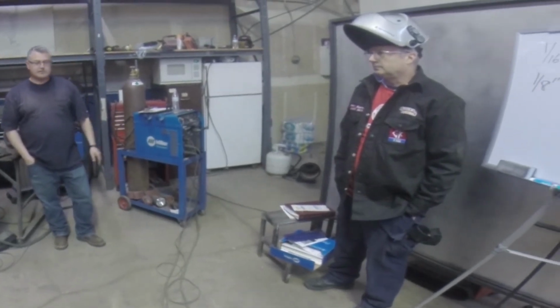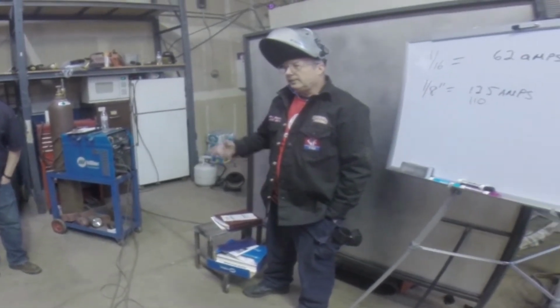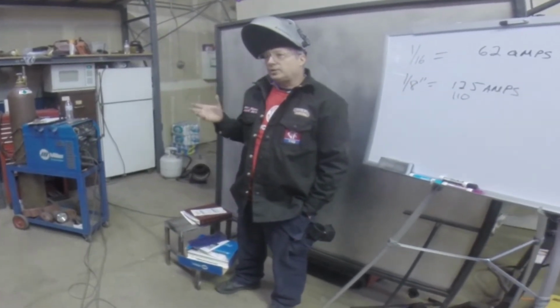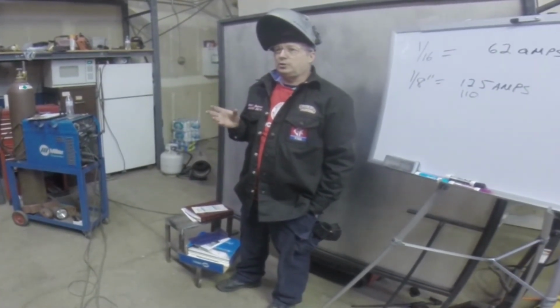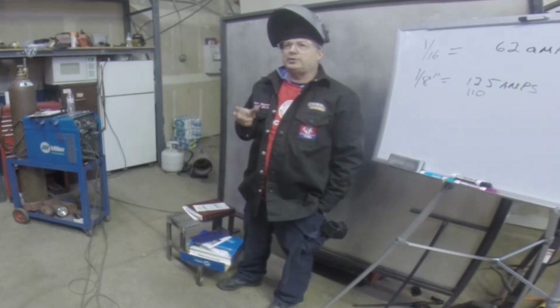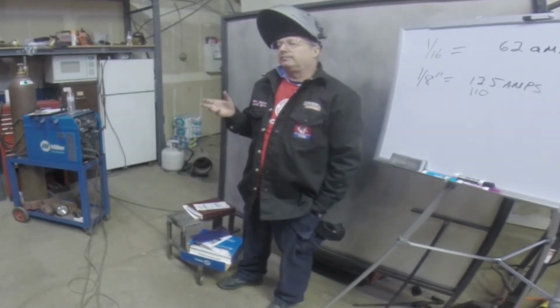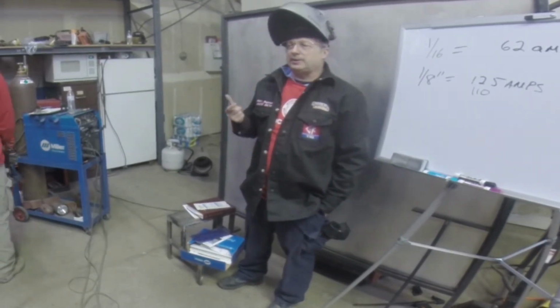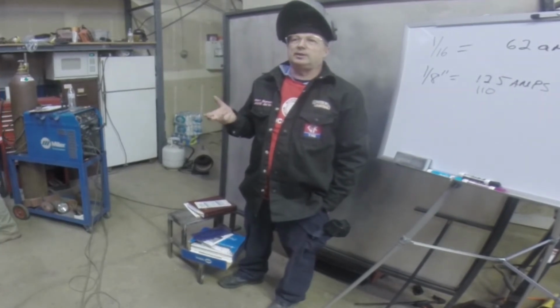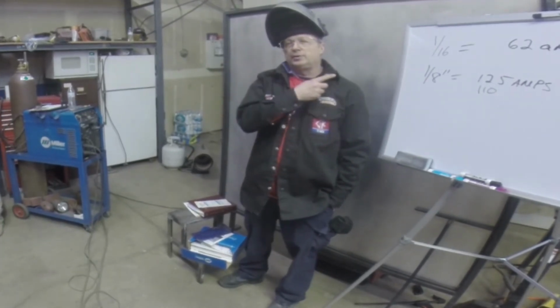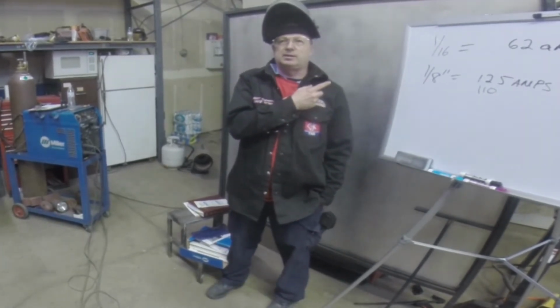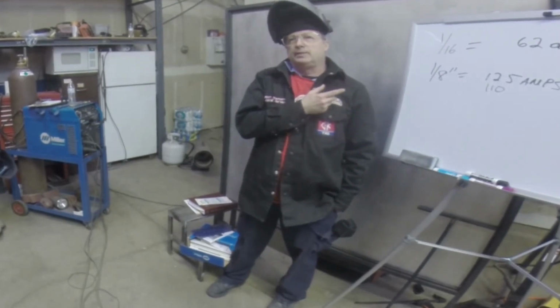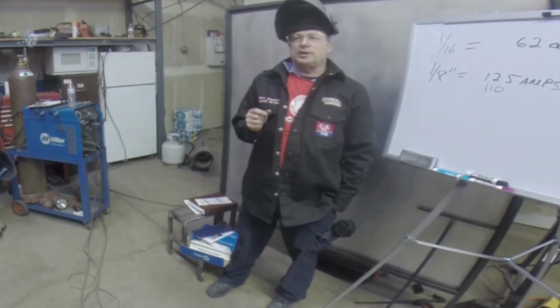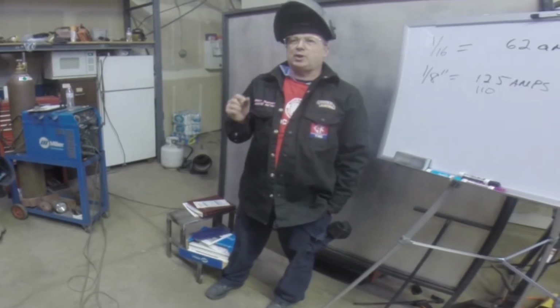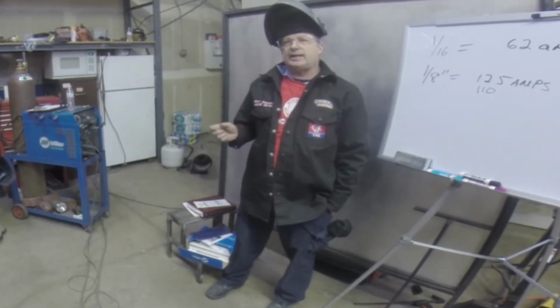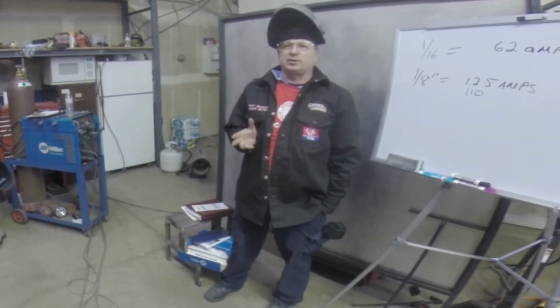It's awesome that Rich is teaching us this stuff. Yes, amperage, like you say, is very critical. In certain materials, you don't want to put too many amps in or you destroy the material. Most of you will probably never see it, but there are materials out there called Hastelloy. There's a company doing a mine outside of Las Vegas, and they're putting Hastelloy piping in. Those welds are so critical, you've got to keep your amps as low as possible and only do stringer beads. Weave beads are not allowed on Hastelloy. The material can crack out.